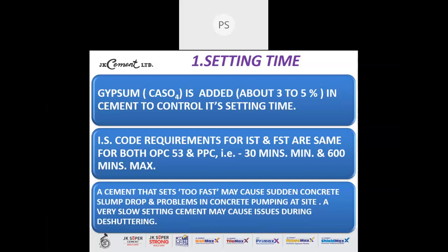Second point, IS code requirements for IST and FST are same for both OPC and PPC, that is 30 minutes minimum and 600 minutes maximum. A third point, a cement that sets too fast may cause sudden concrete slump drop and problems in concrete pumping at site. For example, as I come from Bombay, we have a very high-rise structures and the concrete is produced in one location, for example, Bandra. It has to be transported to another location, that is say Dadar.